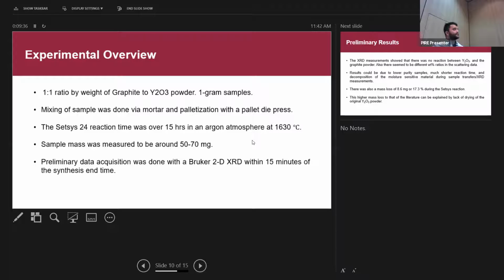But yeah, so I mostly just did 1 gram samples because the thermal analyzer only fits like 50 to 70 milligrams. I sometimes did less than that, sometimes did more than that, but it's very hard because it's just too little. So I mixed the samples using a mortar and I pelletized them using a pellet die press. I don't know if you guys know what a pellet die press is, but maybe I should have added a picture or something.